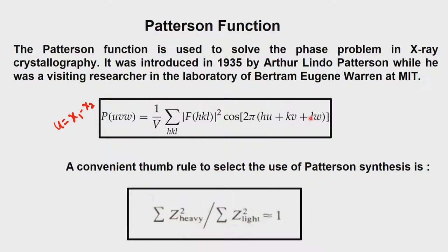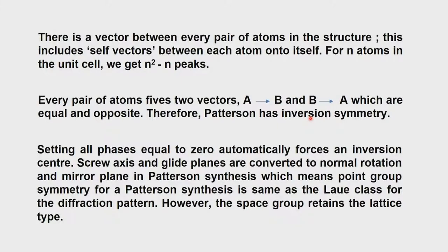When this thumb rule is satisfied, the Patterson function will give us the heavy atom positions uniquely and fairly accurately. When once we have the data giving us the heavy atoms, we can use the over-determined dataset to determine the remaining light atoms using the Fourier synthesis procedure. Heavy atom position is first determined, and using that position we compute F_calc. Then a difference Fourier F_obs minus F_calc is performed — the heavy atom position disappears and the rest of the atoms show up.